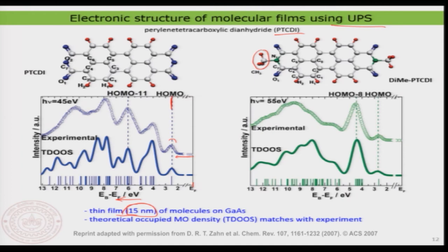Now, you can see clearly that I am doing the UPS on two independent molecules on gallium arsenide, a thin film, and you see that the methylated molecule has a much higher gap from the Fermi energy. The first molecular resonance is coming about 2.5 electron volt with respect to the Fermi level, and in the other case it is a little bit less. That is the clear difference between these two molecules. So, in general you can measure the density of state of the molecule.